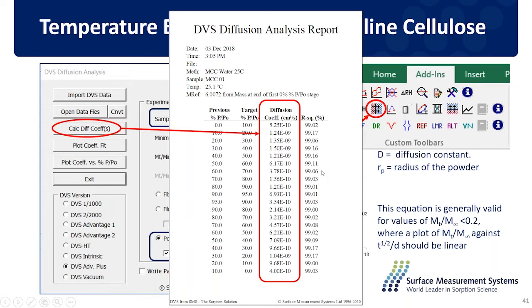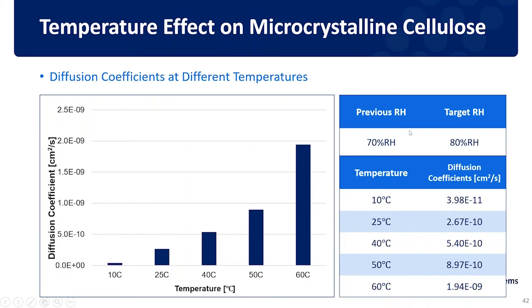So we have different temperature experimental runs, and then we can compare different temperatures at the same stage of relative humidity. Then we can see a very clear trend of increasing diffusion constant at higher temperature for this cellulose material.